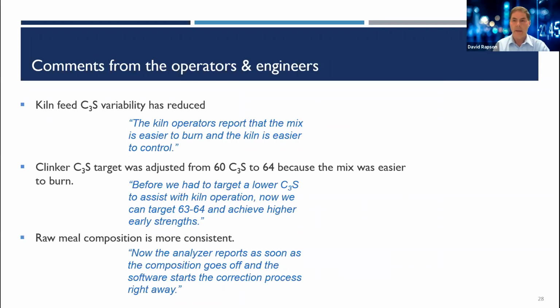The plant staff have made a number of comments about the operation of the plant since the introduction of the automatic online raw mix control system. The kiln operators report that the mix is easier to burn and the kiln is easier to control. Before we had to target a lower C3S to assist with kiln operation. Now we can target 63 to 64 and achieve higher early strengths. Now the analyzer reports as soon as the composition goes off, and the process software starts the correction process right away.